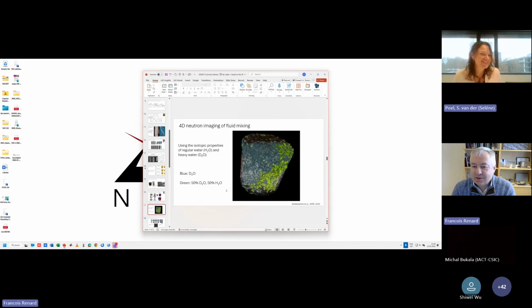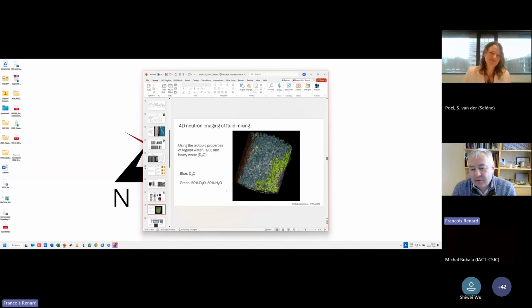That's a very good question, and I think it's an ongoing topic. For me, I still think that this mixing process in a real CO2 operation is relevant. What is injected, at least in CarbFix, for example, is carbonated water, so water rich in CO2, and this water will meet fluids in the basalt that have a different pH, pH 10. They start at pH 4 and then mix with pH 10. And probably it's at the interface between these fluids of different pH that mineral precipitation will occur, will be more favorable. So I still think there is a fluid mixing process. It's just that what I showed you in this movie, we cannot see at depth with this resolution. So that's why it's important to do laboratory experiments.